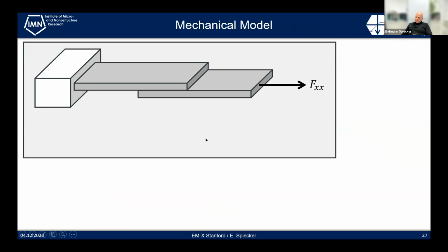Let's finally look at a simple model. So we have here the monolayer graphene and monolayer graphene with the overlapping bilayer graphene region. And we apply an external force Fxx. And there are two counteracting forces, which is a friction force Fr and the cohesive force. So the cohesive force is there because by sliding, you open up new surface area. And this costs energy. This is very similar to this pulling of a nanotube in another nanotube by the Zettl group, where you also have this cohesive force which attracts the nanotube back into the outer nanotube.